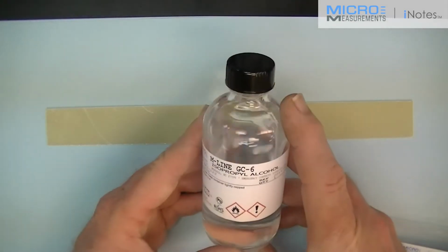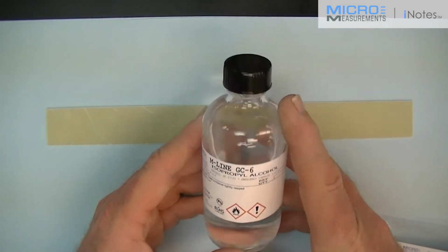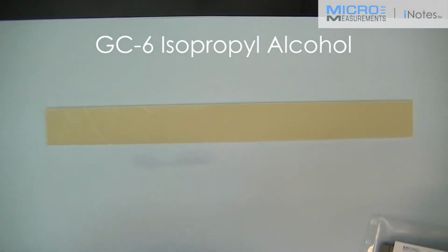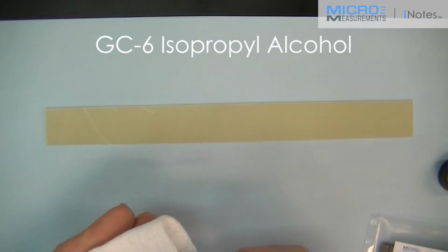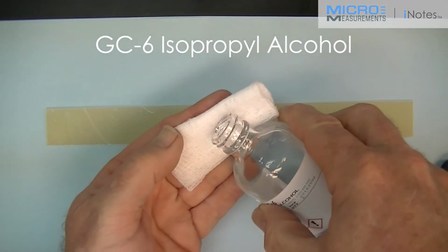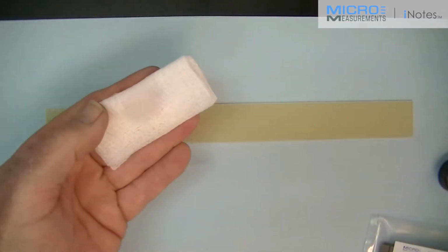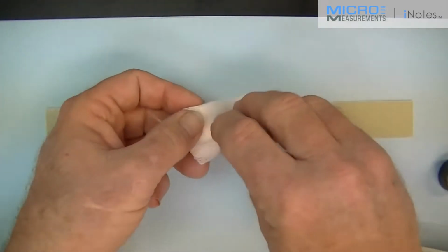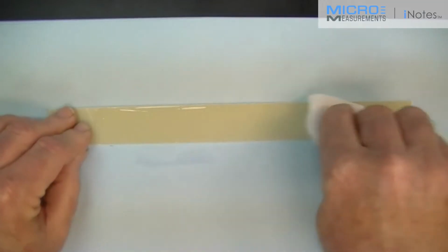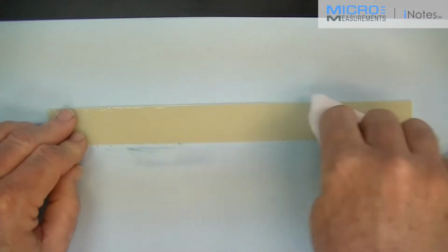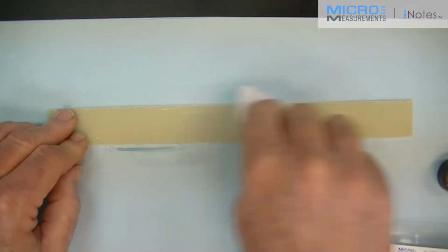We're going to locate the GC6, the alcohol, and because this is a plastic specimen and could be damaged by some of the stronger solvents, the GC6 or isopropyl alcohol is an excellent choice to avoid damage to your part. I'm going to soak the gauze sponge, and then I'm going to degrease the top surface of my beam.